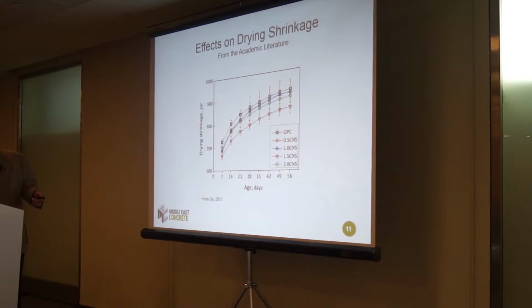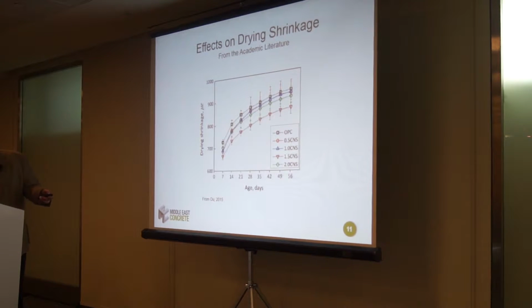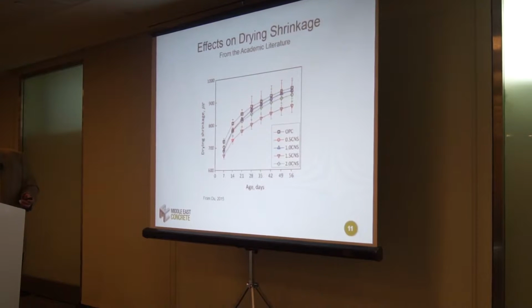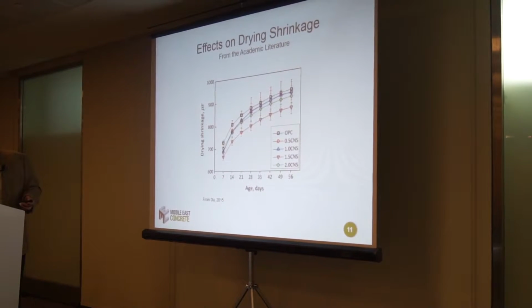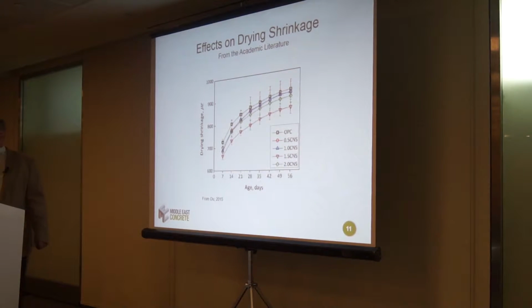And this is a graph from a researcher named Du in 2015. And you can see he has various percentages. These are percentages of colloidal nanosilica. This was actually not a spray applied test. This was done as an integral admixture. But you can see the control is here, ordinary Portland cement at the top, and you can see the drying shrinkage in microstrain decreasing. It looks like the optimum percentage that he found was around 1.5% colloidal nanosilica.